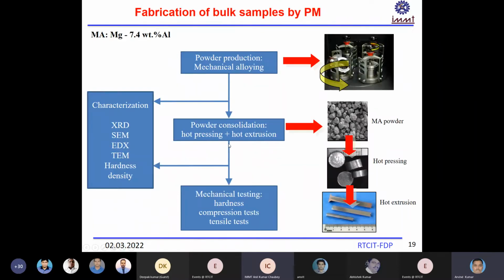I'm going to tell you how this alloy was prepared. We added 7.4% aluminum in magnesium, and by the powder metallurgy route we did mechanical alloying in a planetary ball mill, and then this powder was hot pressed and then hot extruded. After the pressing, you get this tablet form, and this tablet was used again for extrusion, and then you get the rod form, and then the final property of this alloy was evaluated.